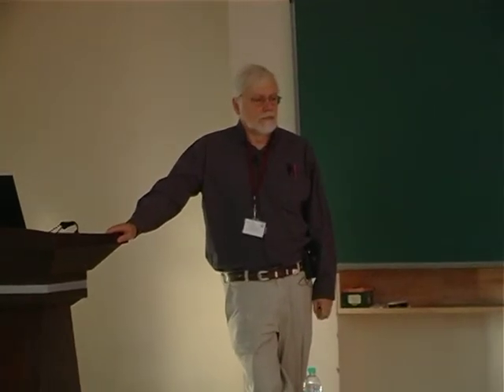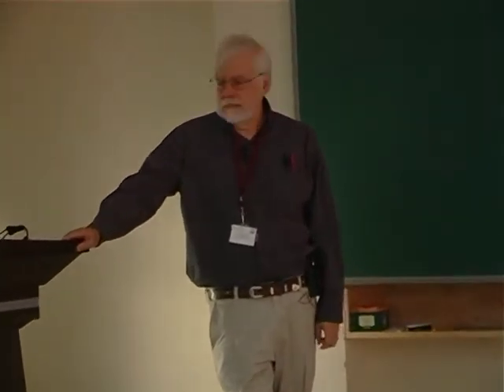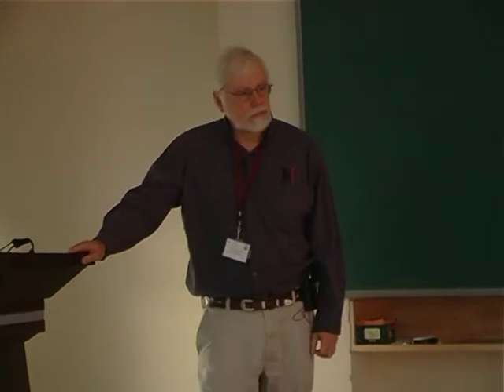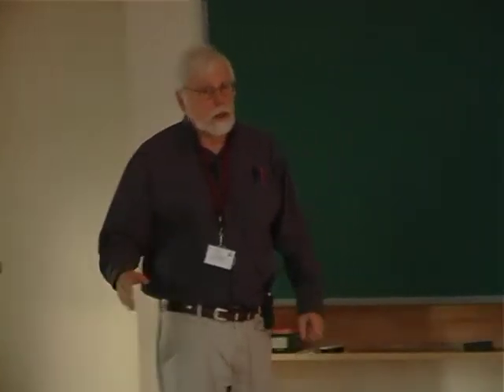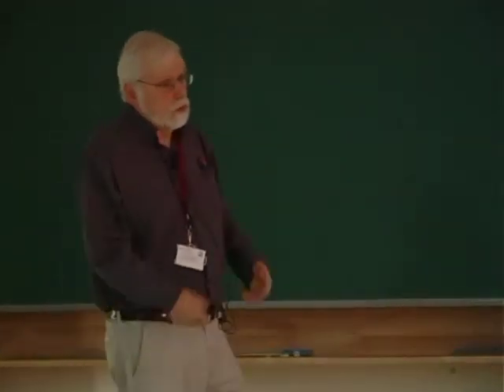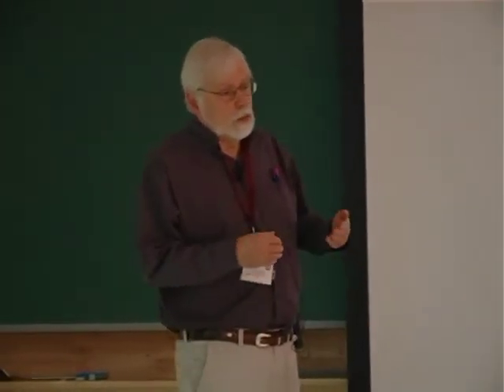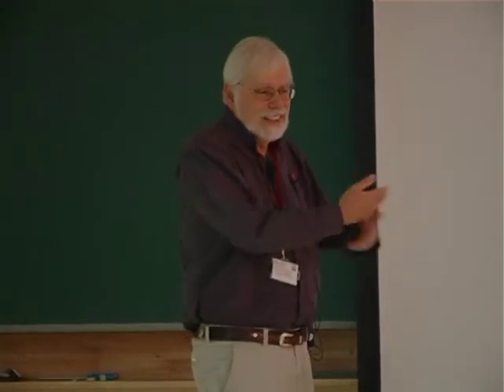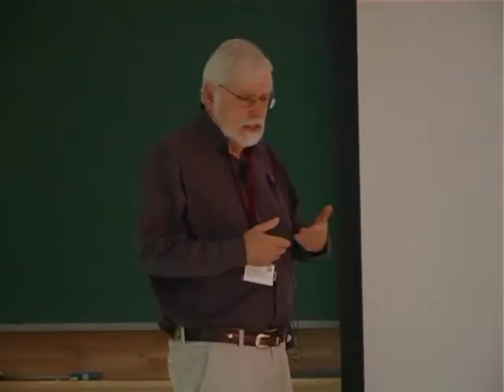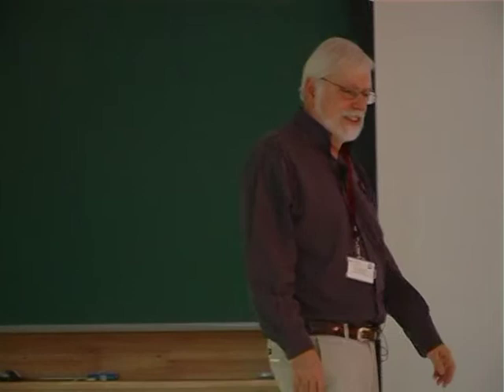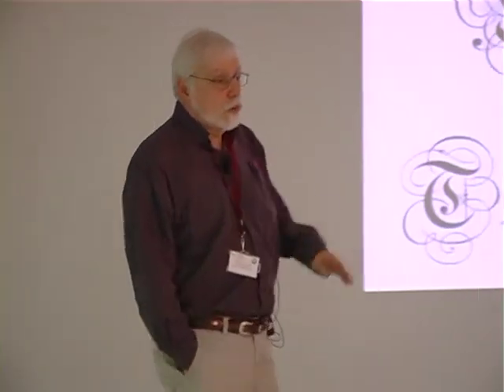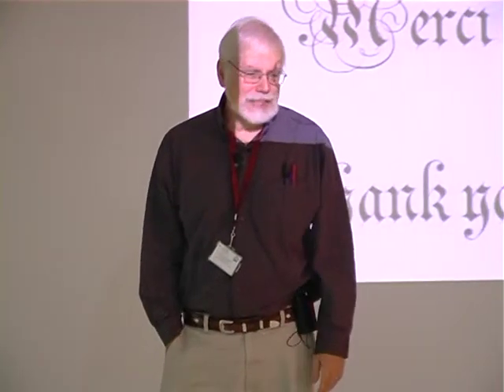Since you find that the V is very important, do you also see this charge density wave in your calculations? Well, that's the next step. We need to see what the implication is for the charge density wave, but then you need to do so-called inhomogeneous CDMFT because it's larger than the cluster. And also anything incommensurate, we will have problems seeing.